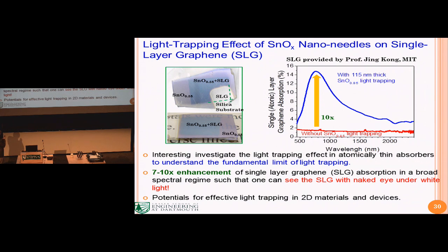When you deposit this single layer of graphene on a silica SiO2 substrate, because graphene has very low absorption, about 1 to 2%, you do not really see that transferred layer. So my students cannot see that either. So Xiaobai just clamped the sample over here during the deposition. So this part has not been deposited with tin oxide nanoneedles. The other places have been deposited, and after you anneal the sample to get the nanoneedle structure, you see a very clear contrast. You see the outline of the transferred graphene layer, and if you extend that, you can see that this part should be graphene, and this part is the silica substrate. Without that deposition, you cannot see any difference, but with deposition, you can clearly see the contrast over here.